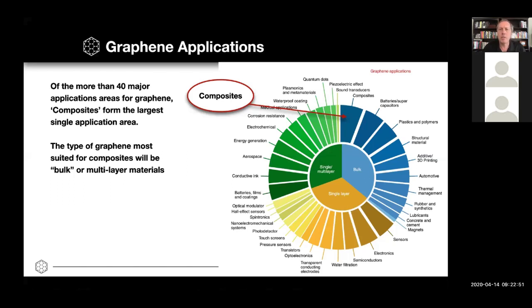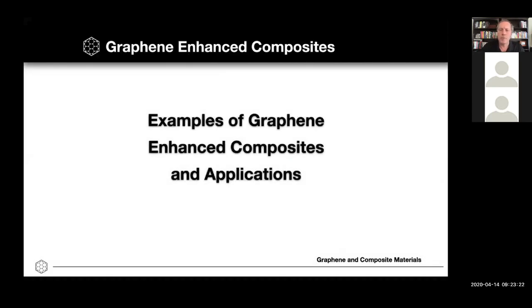An important aspect in understanding graphene is that when it is added in the form of a composite, it's often added at extremely low load factors. So this could be 1% or less, tenths of a percent by weight added into the host material. One of the arguments against graphene has been that it's prohibitively expensive. But when you consider how little of it you actually need to use to drive the performance improvement, it changes that cost dynamic dramatically. So just to run through a couple of examples, and then we'll get to Jason from Composites One to get his perspective as an expert on these resin systems.